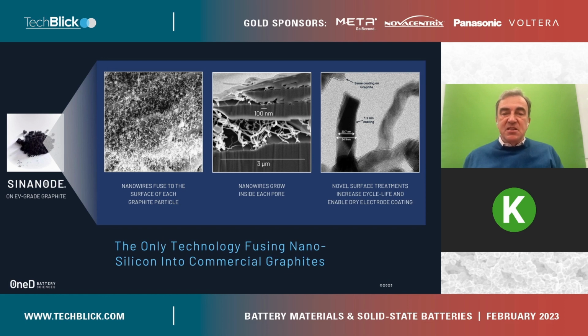And the reason this is plugged this way is because the way we grow those nanowires, in fact, involves a catalyst to make that very fast and very easy. But it results in little roots of silicon being embedded into the graphite layer. Now, what you can see on the slide is that the size of the pore is about, in this case, several micron long, and maybe half a micron or a micron high. And there are many pores like that.